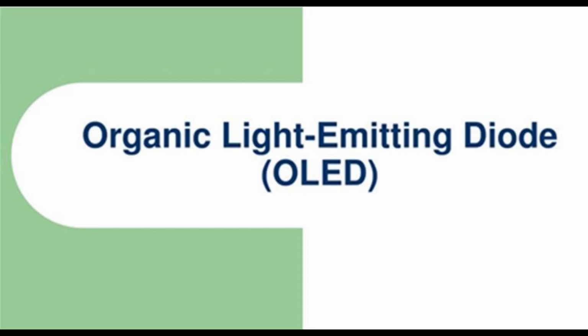For OLED manufacture, after the formation of TFTs for active matrix displays, addressable grids for passive matrix displays, or indium tin oxide, ITO, segments for segment displays, the display is coated with hole injection, transport, and blocking layers, as well as with electroluminescent material after the first two layers, after which ITO or metal may be applied again as a cathode. Later, the entire stack of materials is encapsulated.